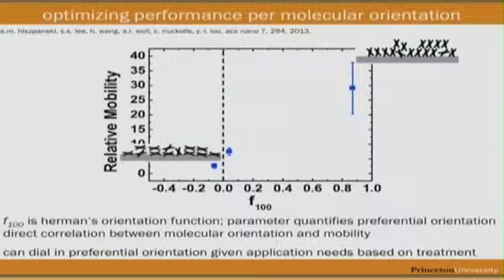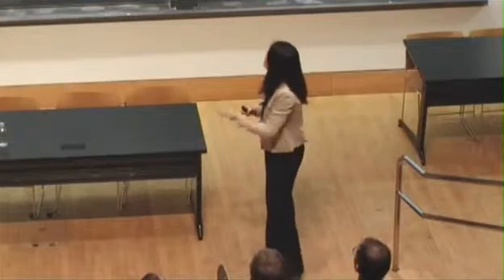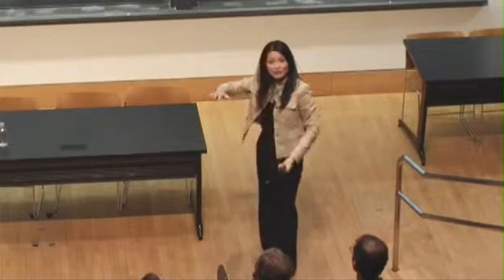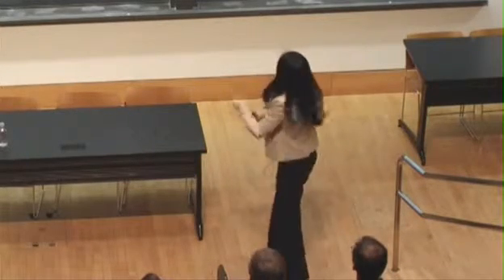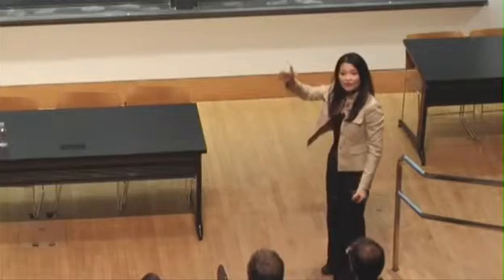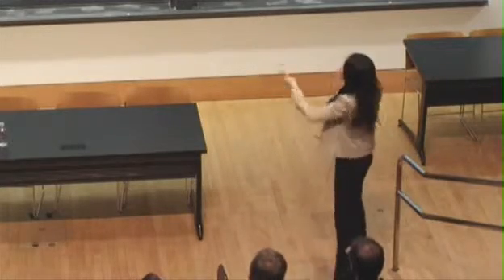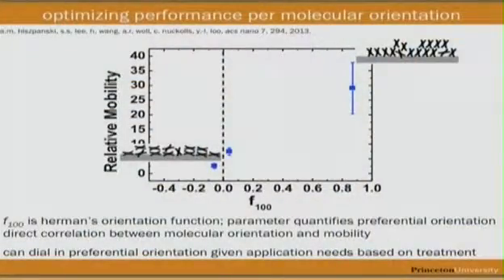So we can sum up what we found by plotting mobility as a function of this F100. This is Hermann's orientation function. It's basically a parameter that can quantify the extent of orientation in our film. So 0 means there's no preference, or it's disordered, or there's no long-range order. Negative means there's a preference for molecules lying down. Positive means there's a preference for molecules standing up. And you can see a direct correlation between the mobility and the orientation of the molecule.